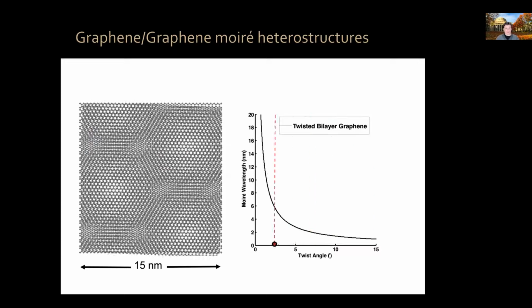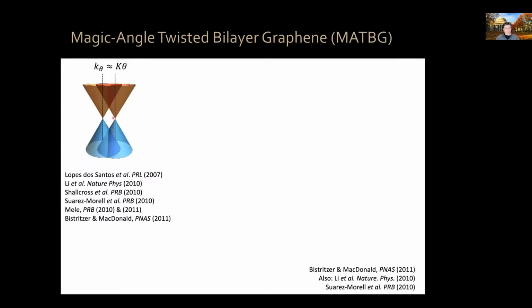So this is the situation already for a small twist angle between the 2 graphene sheets. This is the graphene Dirac cone of graphene sheet number 1. This is the graphene Dirac cone of graphene layer number 2. And as you can see, this is a situation that would be the case if the 2 graphene sheets did not know that each other exists. However,